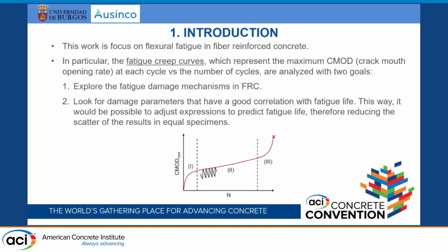So in this case, our research has been focused on flexural fatigue and a particular result that we obtained from flexural fatigue, which is the fatigue creep curves, which relate the number of cycles versus the maximum CMOD. We are talking about flexural fatigue in notched specimens. So this is the curve that correlates maximum CMOD in each cycle against the number of cycles.